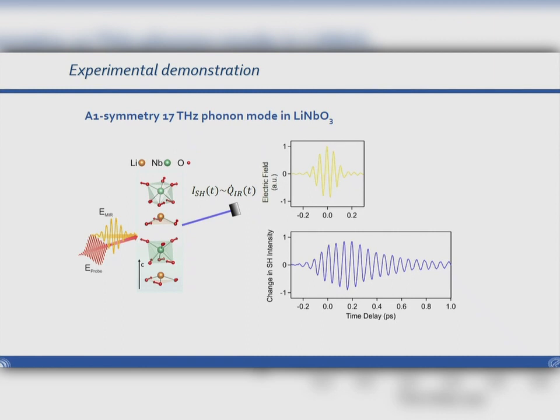So this is a typical electric field that we are able to generate in our tabletop experiments. So this is a two-cycle field tuned to a frequency of about 17 terahertz. And here, in this particular situation, this is in resonance with a certain phonon mode in lithium niobate. And if you do a time-resolved measurement using second harmonic, that we have also seen before, that measures the breaking of inversion symmetry in this material, you can perfectly see what I just described before in this theoretical calculation.